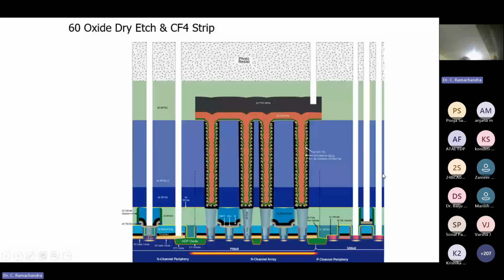When these holes are very thin, like 0.2, 0.5 micron, even if I assume a few ions go inside and react, it will generate byproduct. Then what is the probability this byproduct comes out? If this byproduct does not come out and stays, then my whole purpose is defeated. So removal of the byproduct is equally or more challenging in etching. Therefore, I need to optimize so many parameters and make sure that enough ions go inside to etch and these byproducts are volatile and they come out. These two criteria have to be met, which is very, very difficult and challenging.